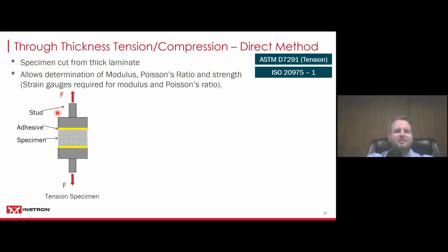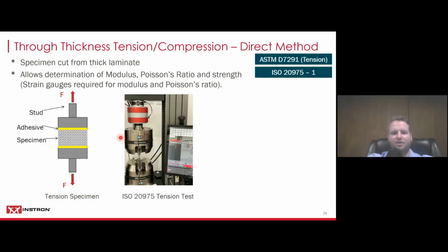So you usually have a stud that you can pull on, and then you adhere your specimen to it. You take your thick specimen and glue it to the studs on the top and on the bottom, and then you apply the loads here and pull this apart in tension, and you want the failure to happen somewhere here in the middle. That gives you the through thickness tension and compression strength, and these are the direct methods.